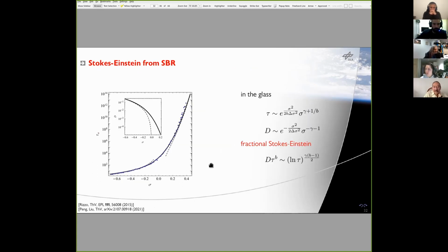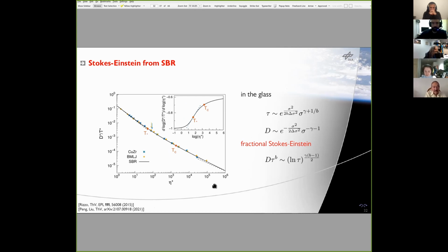And I've actually included this plot again. Tommaso has shown it. So this is the relaxation time as a function of the distance parameter from SPR. And if you work out the Stokes-Einstein relation, this is the typical plot that you do there. You plot the normalized diffusion coefficient as a function of the viscosity, and Stokes-Einstein would be a linear 1 over viscosity law. And the theory predicts this to cross over to a fractional Stokes-Einstein law. I'm just showing this because there's by now also a nice fit to another two data sets of computer simulations that Hailong Peng calculated in a collaboration with us. So this works rather nicely.